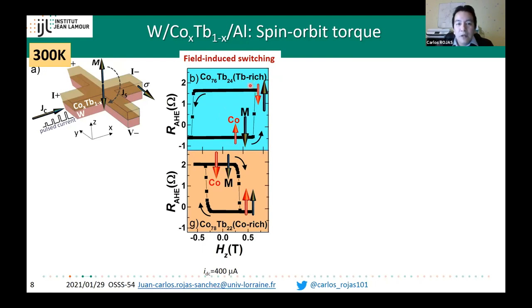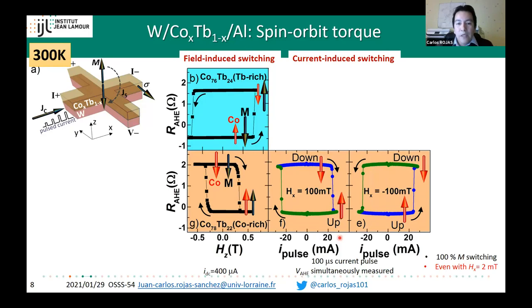One sample is terbium-rich and the other cobalt-rich at room temperature. They have opposite field-induced switching polarity with a small sensing current of 400 µA. Instead of using a perpendicular field, we now use an in-plane current, and we observe a nice cycle showing spin-orbit switching of the perpendicular magnetization with a sharp jump at the critical switching current. Changing the sign of the in-plane field reverses the switching polarity, consistent with spin-orbit switching, and we achieve 100% magnetization switching.